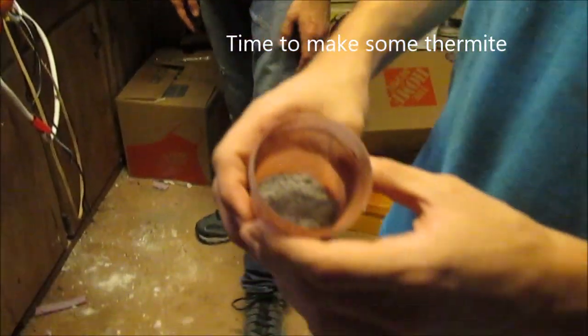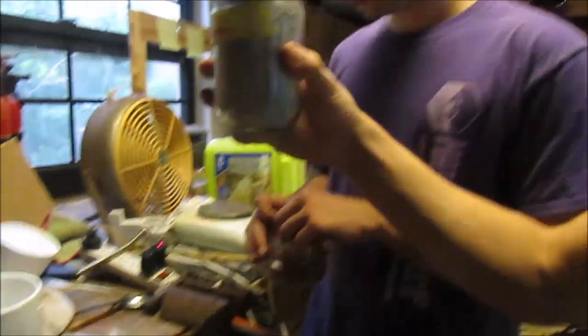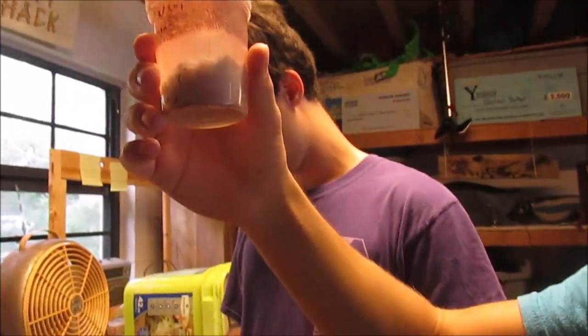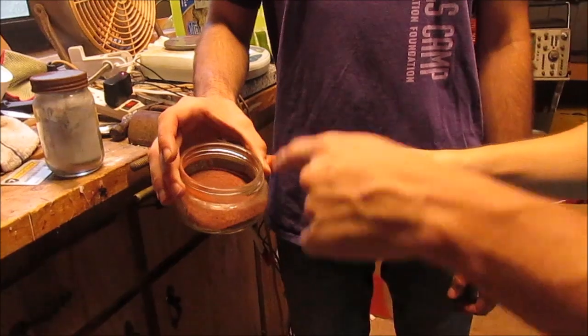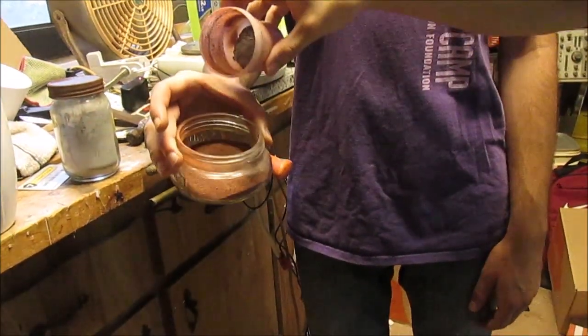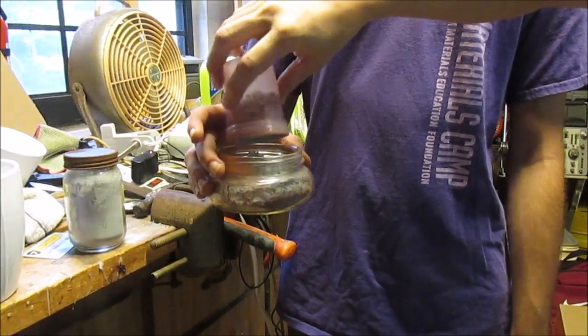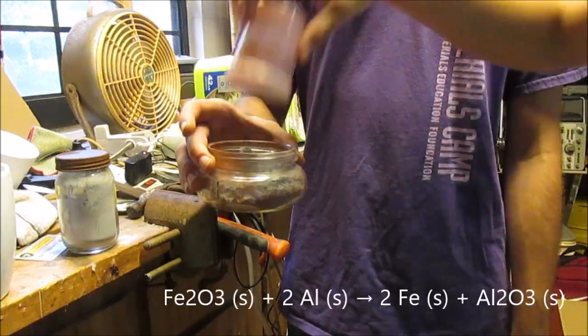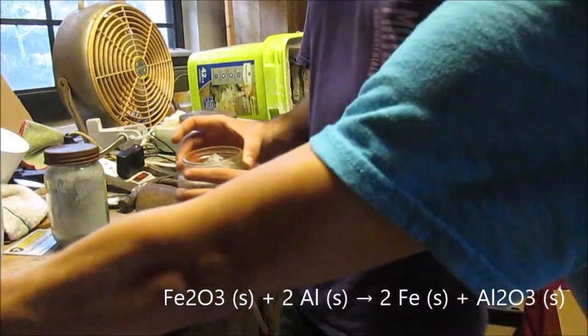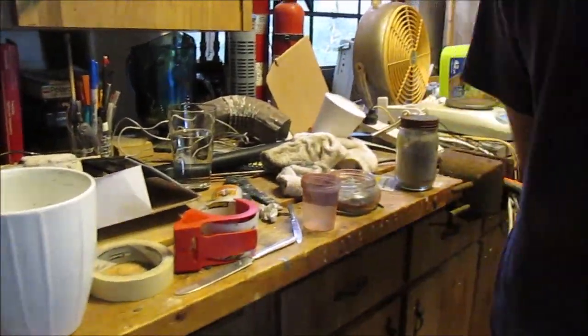What's inside here? Now, you see that gray color? That would be some aluminum powder. What's under it? Iron oxide. That's right. This is the iron oxide — it's 100 grams of iron oxide to 33 grams of aluminum, because it's supposed to be a three-to-one ratio. So now we've got those put in there, let's get a good mix on. We're approximately at 2.96, but nobody cares. We have slight excess, so it actually works in our favor.